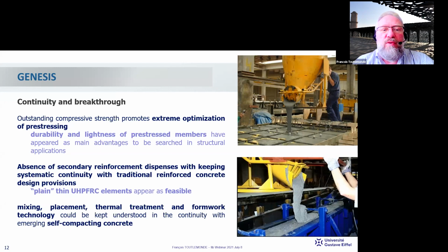So UHPFRC was understood, I would say, both in continuity and as a breakthrough. So the outstanding compressive strength properties promoted an extreme optimization of pre-stressing. And so the durability and lightness of pre-stressed members have appeared as main advantages to be searched in the structural applications. The absence of secondary reinforcement dispenses with keeping the systematic continuity with the traditional reinforced concrete design provisions. And so the trend was to develop plain thin UHPFRC elements which appear as feasible.